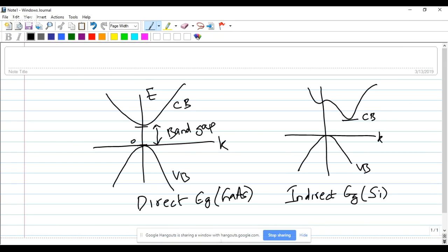Silicon works great when you're looking only at electronic properties. Its band gap is 1.1 eV, which means it is fairly stable at room temperature. You can get good conductivity by doping. Silicon also comes from silica, which is a very widely available material. That is why silicon is used for most electronic applications.